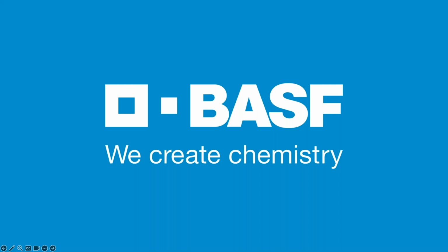Is the product delivered with components mixed, or is there any chance for excess isocyanate that might be a concern with groundwater? Well, the materials are not mixed prior to injection in the ground. You would have the resin, which is the blend of polyol, catalyst, and so forth that Kyle had mentioned, and then the isocyanate is separate. The isocyanate does react with moisture, so if there is any spill on the surface, it would react to form urea, which can be dug out. But in what we've seen with proper handling, that's not been an issue.